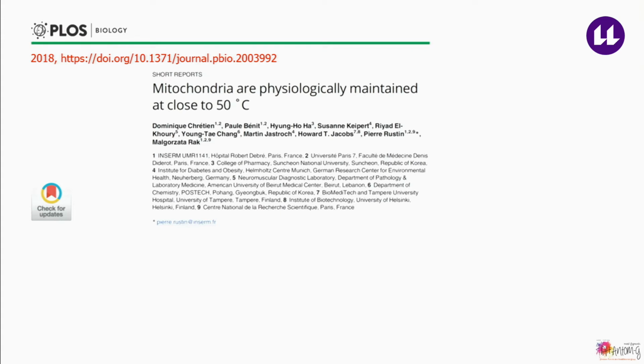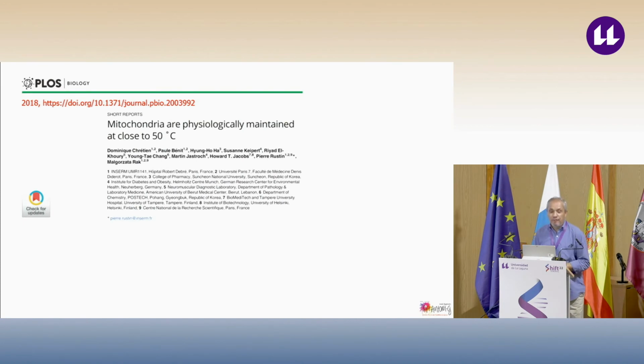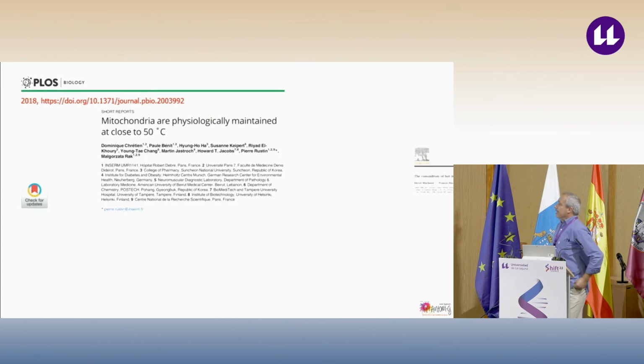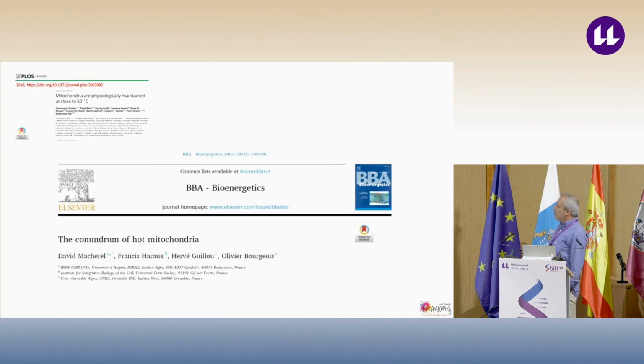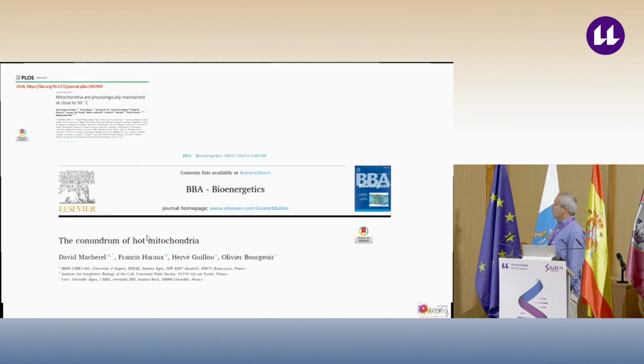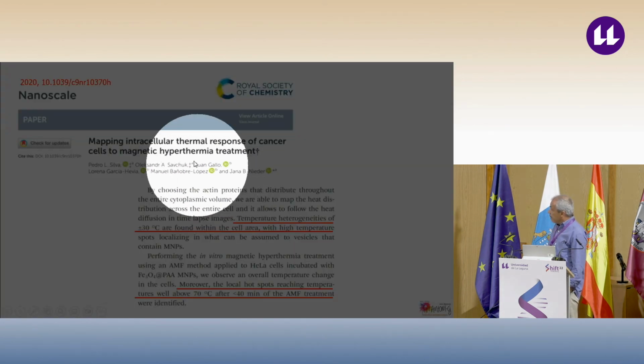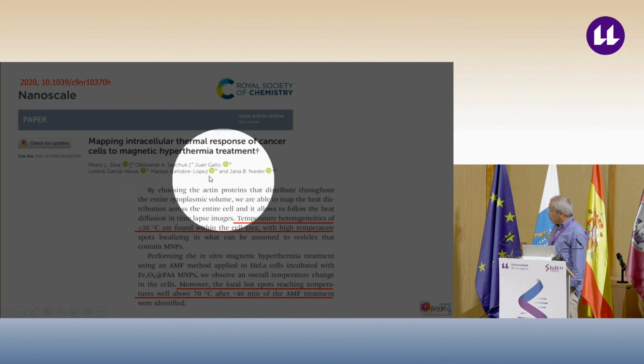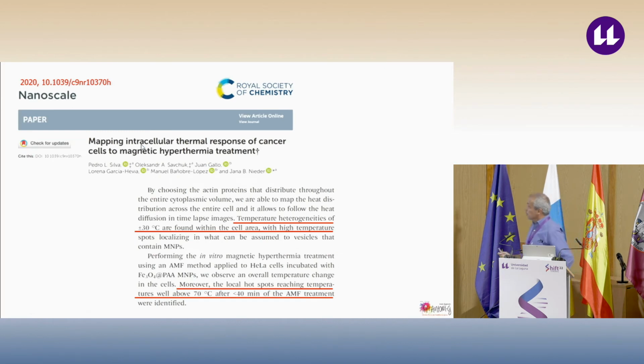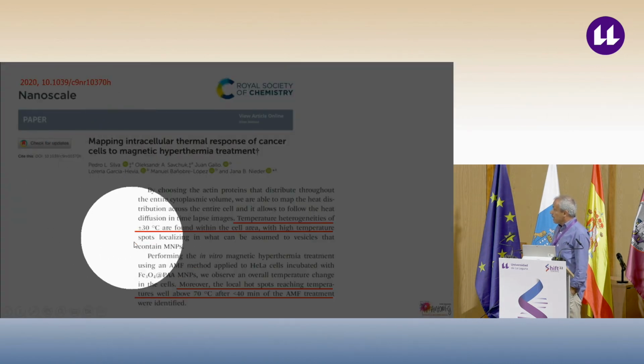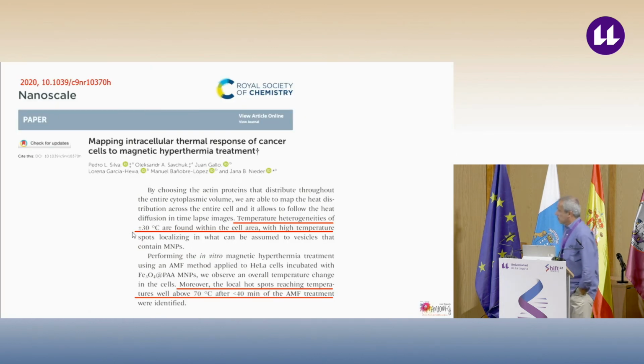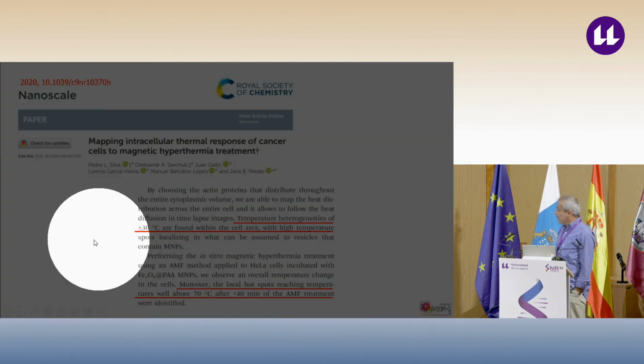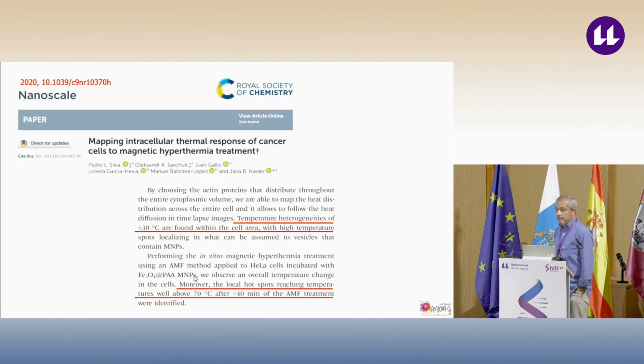This paper is very interesting because the authors argue that the mitochondria work at temperatures close to 50 degrees. And there is a review paper that discusses this problem. Second example, this is a paper from a group that, by the way, works in Portugal. They use magnetic hyperthermia experiments, and they conclude that they have temperature heterogeneities around 30 Celsius, and when they apply the alternating magnetic field, they can reach temperatures above 70 degrees.